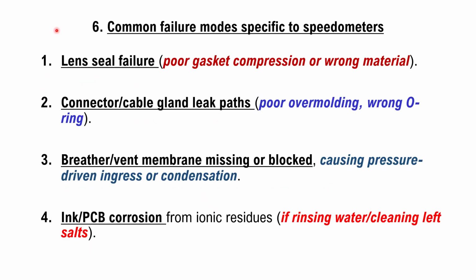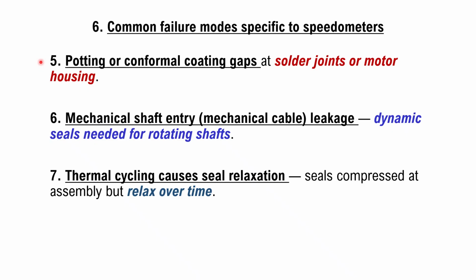What are the common failure modes specific to speedometers? The common failures are lens seal failures, connector or cable gland leak path, breather vent membrane missing or blocked, and finally PCB corrosion. Other failure modes could be potting or conformal coating gaps, mechanical shaft entry, that is mechanical cable and leakage, where a dynamic seal is needed for rotating shafts, and thermal cycling causing seal relaxation, that is, seals compressed at assembly but relaxing over time.